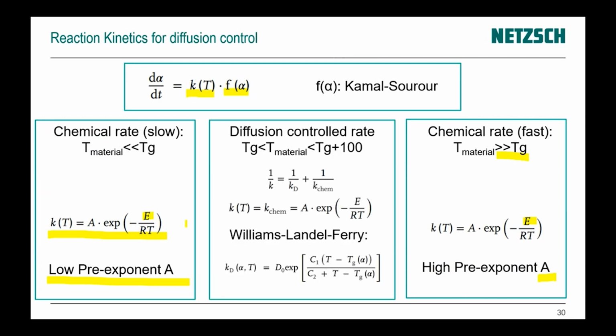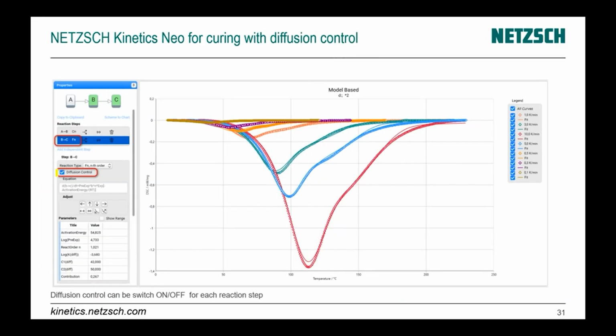And if we are somewhere in the middle, then our reaction rate K depends on 2 parts. The first one is a chemical part, which is just a normal Arrhenius equation. And the second part depends on diffusion, according to Williams-Landel-Ferry with some constants, C1, C2, which are unknown. And this is the mathematics inside the software. You can calculate, of course, manually. It costs you several days for evaluation of each curve. Here in the software, we just make one-click diffusion control.